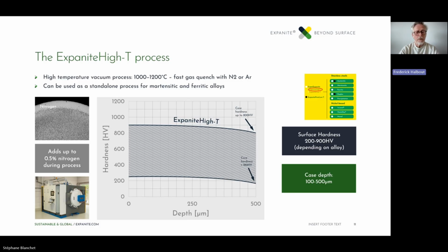In this step, we dissolve nitrogen into the material, and due to the high temperature, we have a deep diffusion of the nitrogen, increasing the hardness of the core somewhat, with a reach of up to, it says 500 microns here, but for austenitic stainless steels, there is actually up to 1,000 microns diffusion depth. Once the diffusion has been done, there is a quick quenching with either nitrogen or argon to get a stable situation and no transformation of the material during cooling down. So we need to do a fast quench.